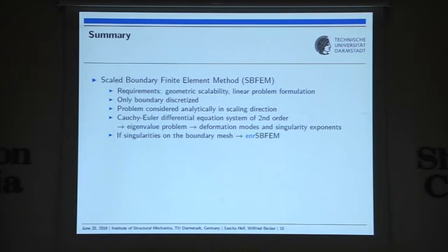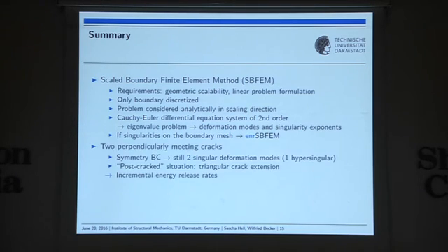And in the case that singularities are present on the boundary mesh, the enriched SBFEM should be used. Okay, and using this enriched SBFEM, we considered the case of 2 perpendicularly meeting cracks with symmetry boundary conditions, so that we only keep 2 singular deformation modes, of which one actually is hypersingular, so stronger than the classical crack singularity. And as a post-crack situation, we introduce a triangular crack extension and calculated the incremental energy release rates.